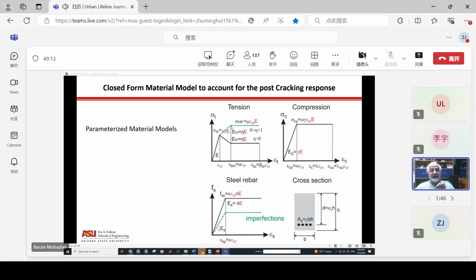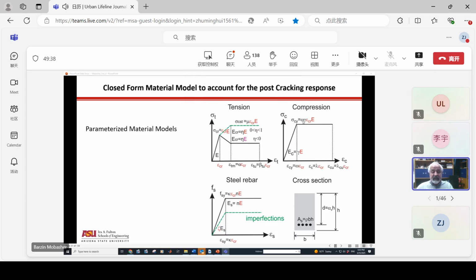So if I have a slope that's positive or slope that's negative, I want to represent it by parameter eta. If I have a constant stress in the post-peak response, I want to call it parameter mu. So that's a number like 0.5, 0.6. Eta can be 0.1, which means that only 10% of the strain is retained after cracking. Also, compression should be expressed in this term. So I define parameter omega to represent the compressive strength to tensile strength. So its number is equivalent to, let's say, 10 or 12. So the concrete is 12 times stronger in compression than tension.